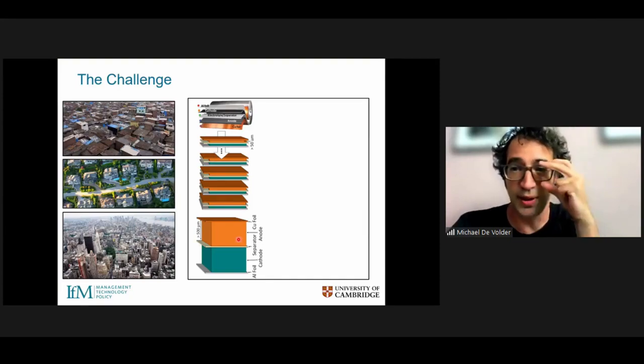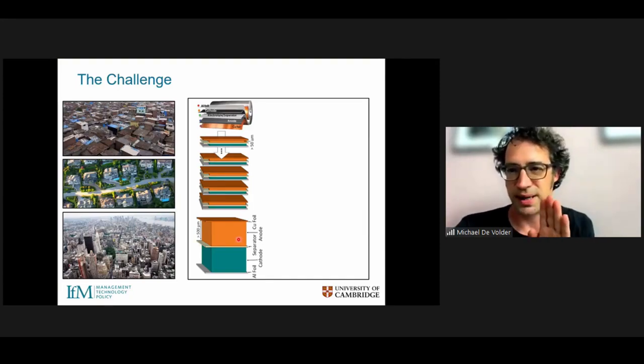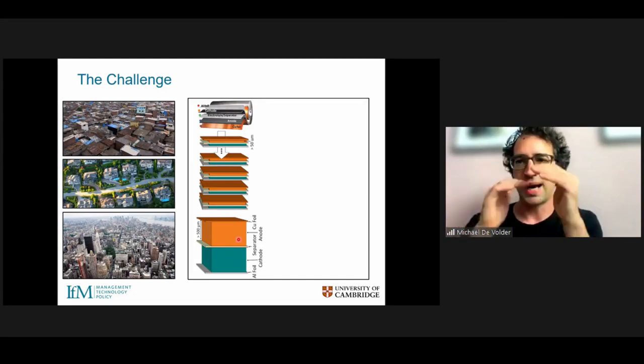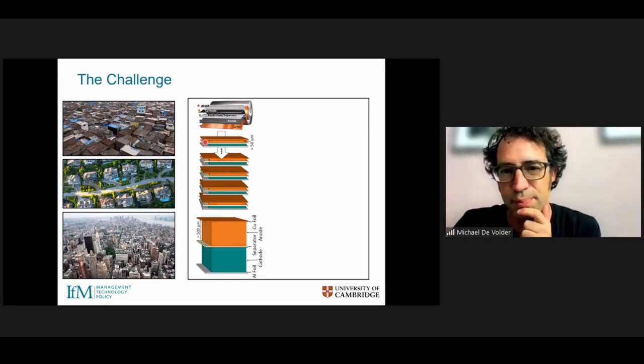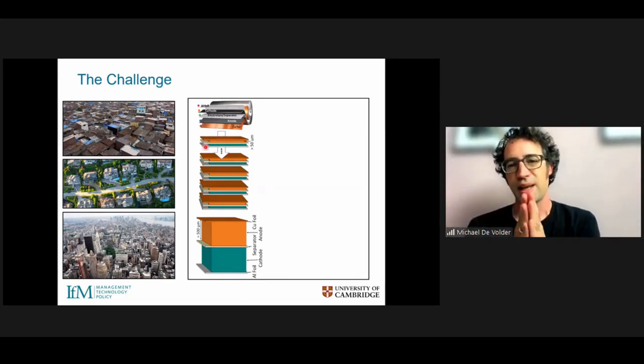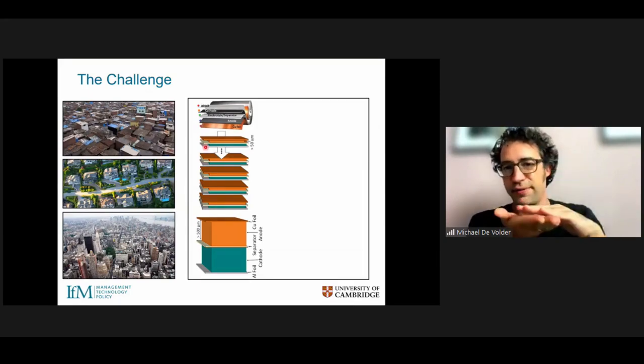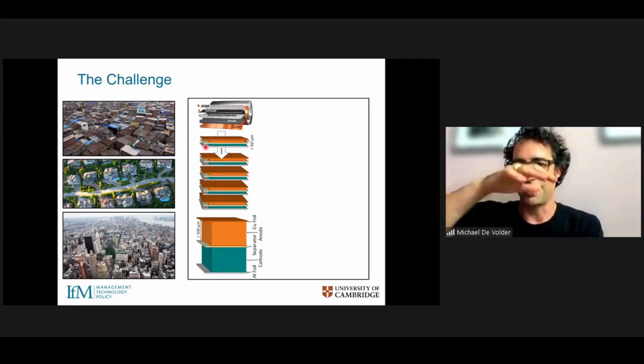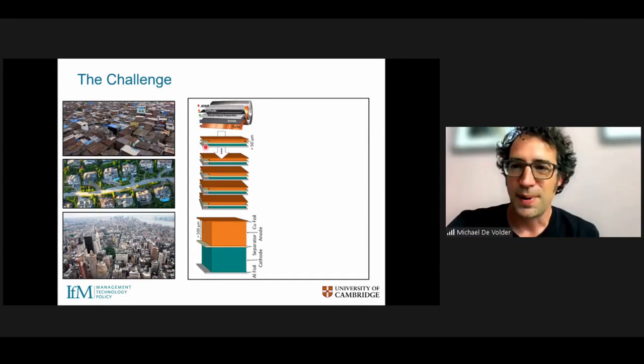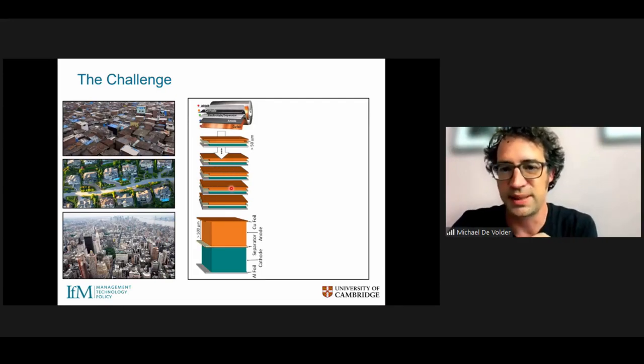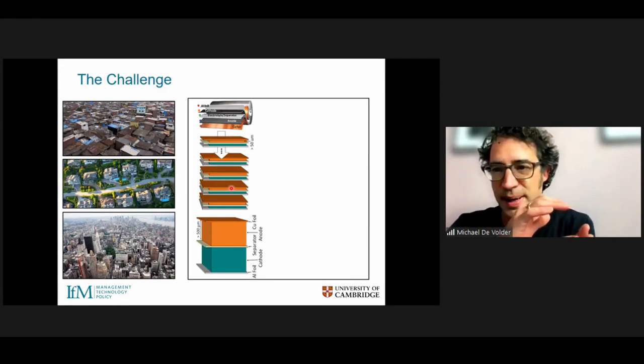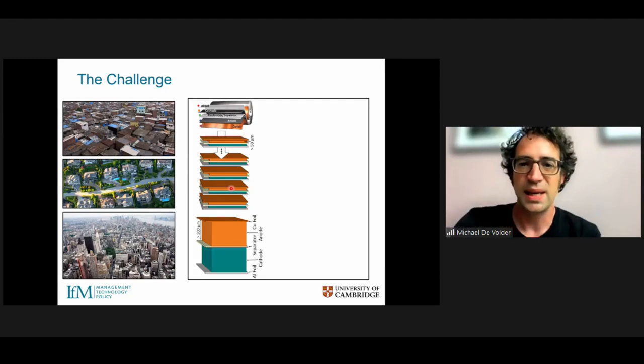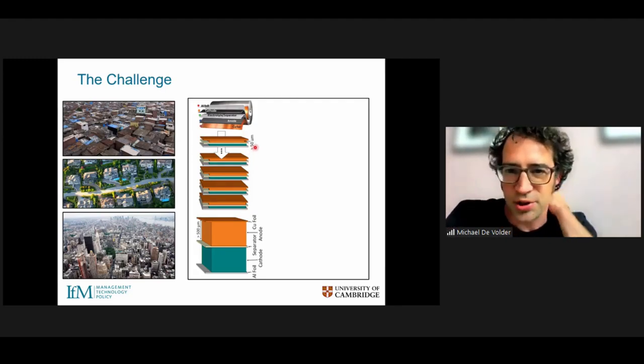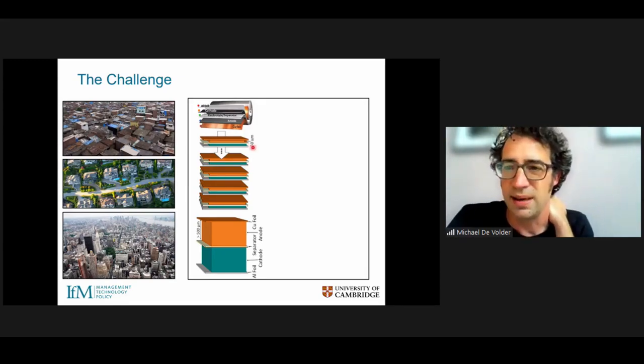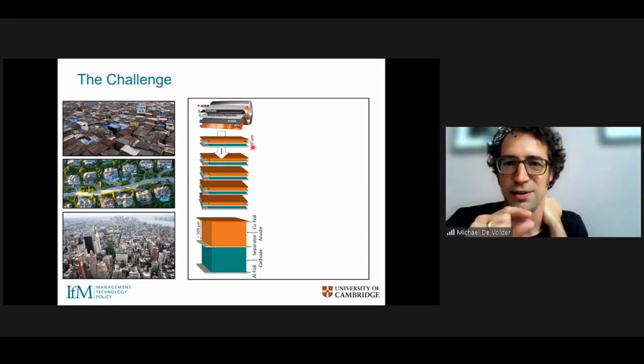So why is this interesting? Well, if you think back of the cross-section I've shown you of a lithium-ion battery, you'll remember it was this stack of anodes and cathodes, and in the middle we had these separators and metal foils. Now, if we can increase the thickness of our electrodes and make them a three-dimensional thick electrode, what happens is that we need less separator and metal collector foil materials relative to the battery materials, which actually help storing the energy. So just to give you some numbers, in a typical commercial battery electrode, the electrode thickness would be about 50 micrometers, so about the same thickness as human hair.